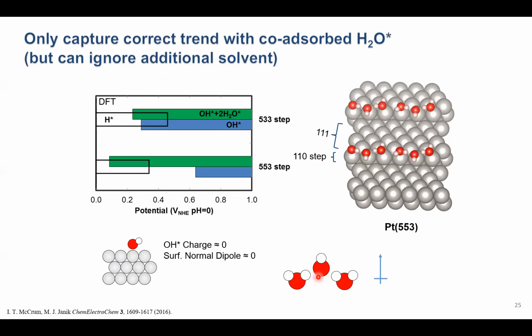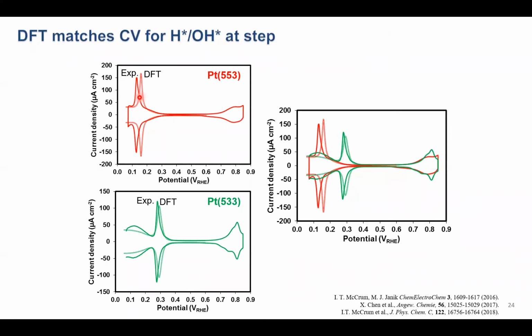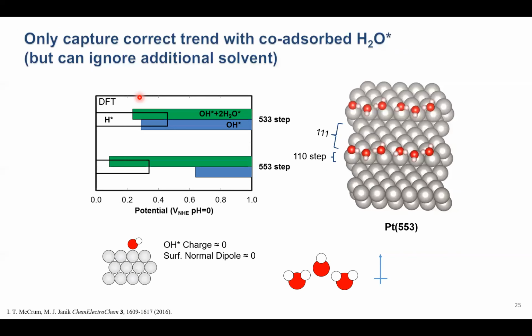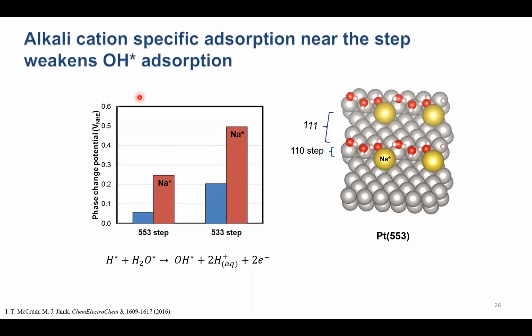But we have to keep in mind hydroxide has its own internal dipole moment, which makes it very favorable for water to co-adsorb with that hydroxide on the step. And when it does, it forms these strong hydrogen bonds, and that promotes hydroxide adsorption relative to what we find in vacuum. And notice that the trend in which surface binds OH more strongly is different whether we ignore that effect of solvation or include that effect of solvation. And so for OH, we needed to consider solvent decomposition and this kind of solvating effect. Importantly, once we included the co-adsorbed water, we matched experiment pretty well. We didn't need additional water above the surface to capture this effect. And so now we know what's going on in these step peaks.